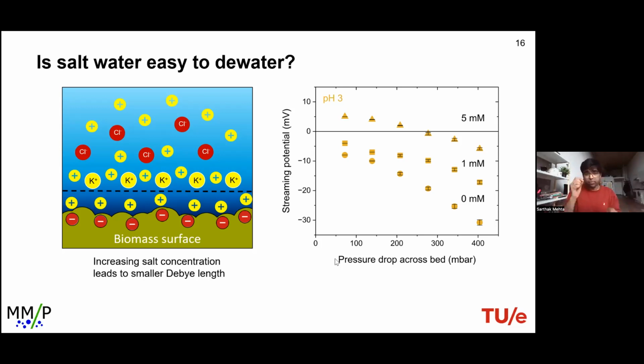One thing to note here, which is very peculiar, is that as I increase the salt concentration, I see a reverse in polarity, as you can see for a 5 millimolar KCl solution in pH 3.